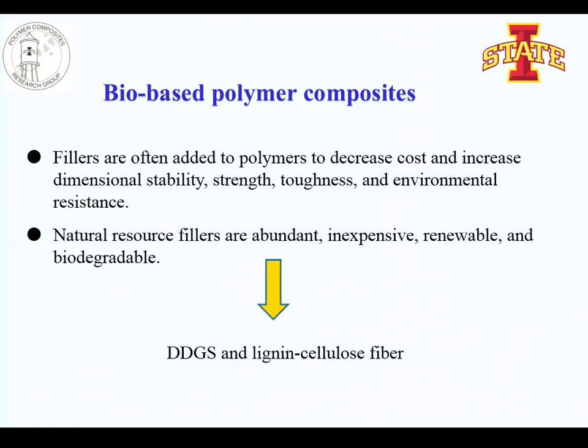We also add filler to biobased polymers to increase dimensional stability, strength, toughness, and environmental resistance. Most biobased fillers are abundant, inexpensive, renewable, and biodegradable. For our project we use DDGs and lignin cellulose fiber. DDGs is biodegradable but lignin cellulose fiber is not. These fillers are very cheap, and adding them to biobased material will increase the degradation rate and decrease the cost.